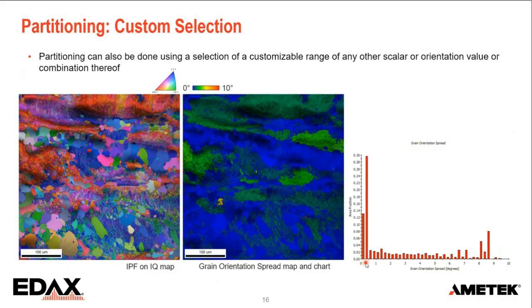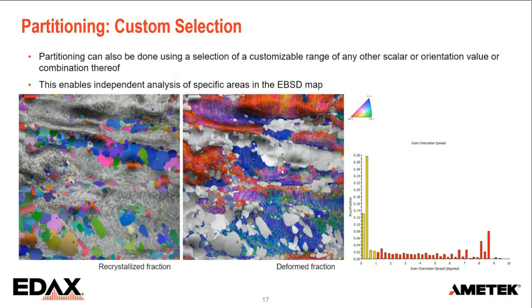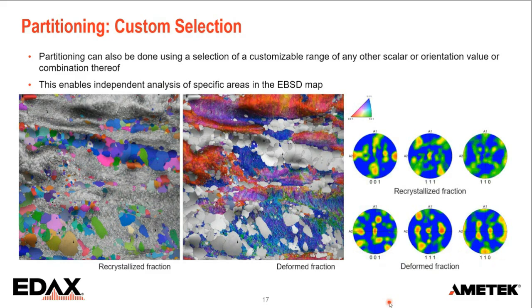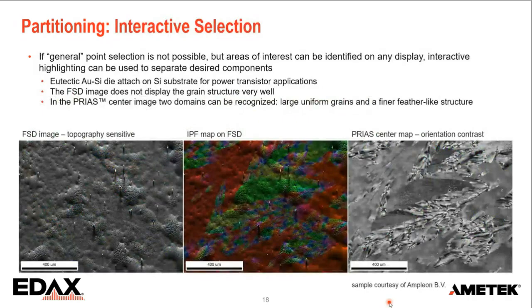And when I just select those, so I can just select a fraction, that allows me to interactively split the data set into 2 components that I can then analyze separately. So here I have just an IQ map on both sides with a color coding of the selected fraction. And for example, for both fractions, I can calculate a texture just to see how this microstructure evolved. And sometimes even that is not possible. Then you can do an interactive selection directly on the map itself.